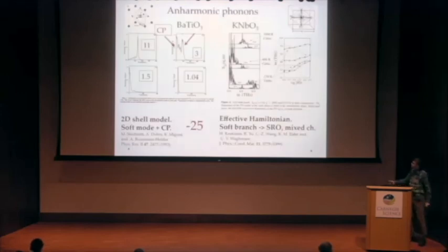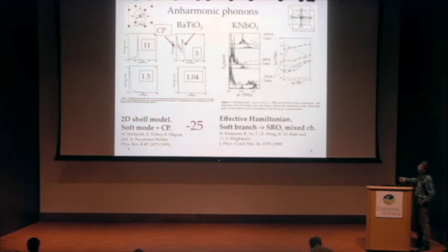Now, about the same time as the first principles calculations appeared, there was also a question: what happens with the unstable mode at high temperatures? These are simulations at finite temperatures, which show us the spectrum at 11 times Tc, 3 times Tc, 1.5 Tc, and almost above Tc. What is the dynamical structure factor, the frequency and intensity?